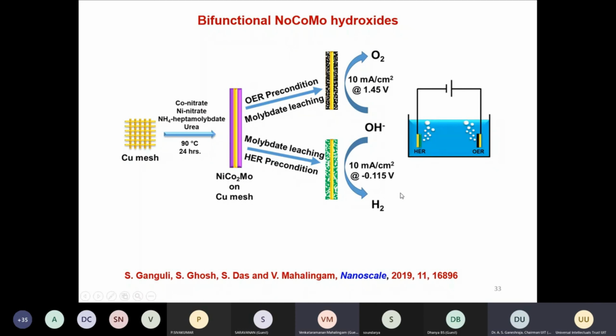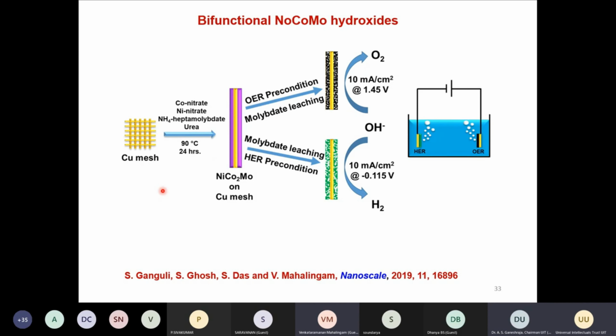So next, I will show an example of a bifunctional catalyst with nickel, cobalt, and molybdenum hydroxide. We wanted to do this directly on copper mesh, instead of nickel mesh, which is used in most studies and is quite expensive. Also, most of the nickel, cobalt based materials are made by a hydrothermal route. So we thought if we can make something at a lower temperature with a simple process, it can be extendable and scalable. This is the idea with which we have done this copper mesh study.